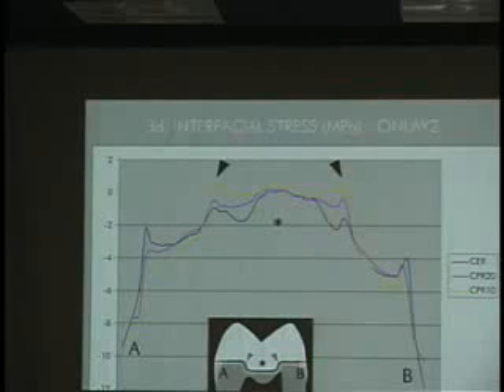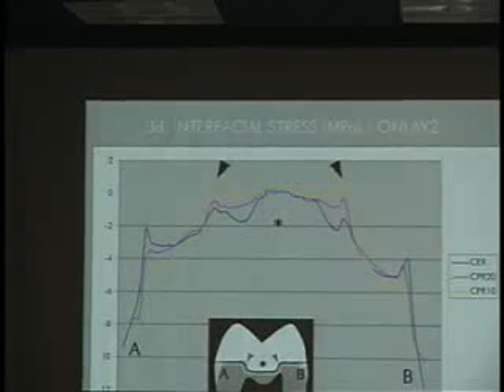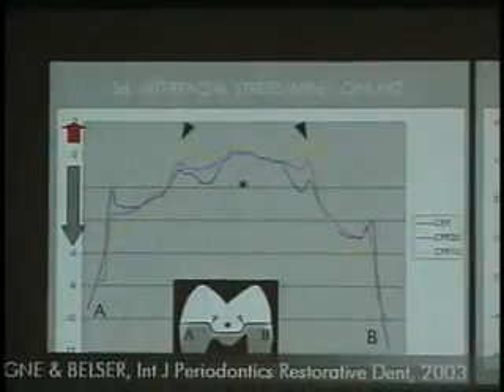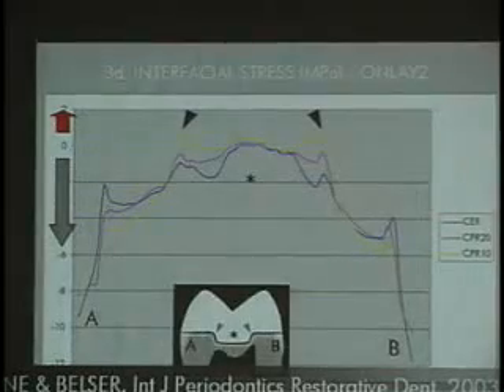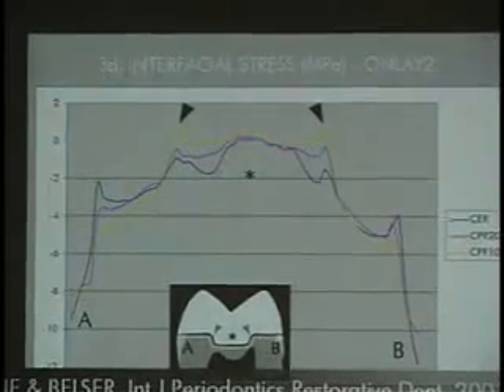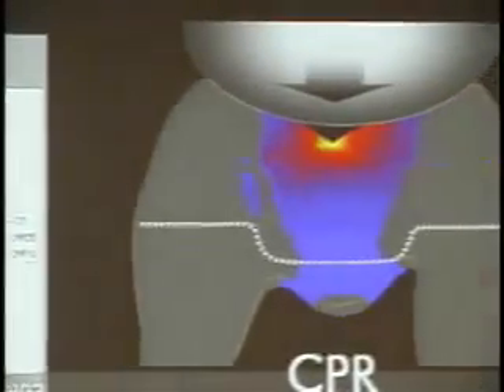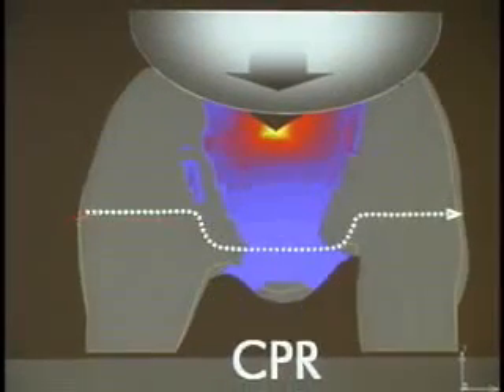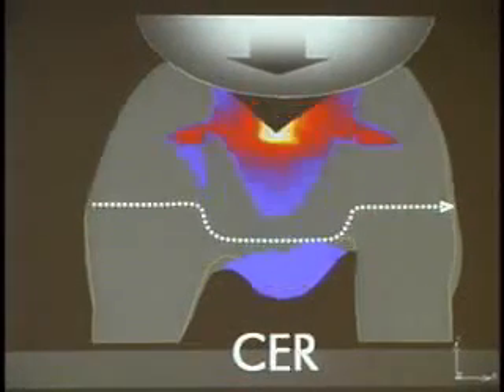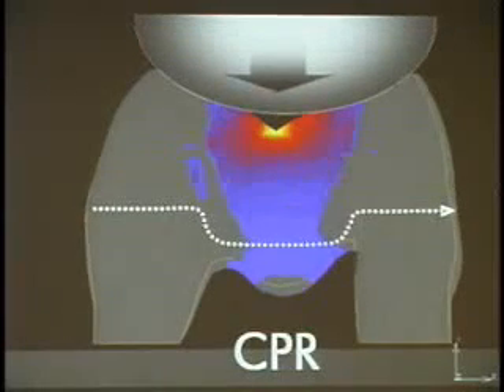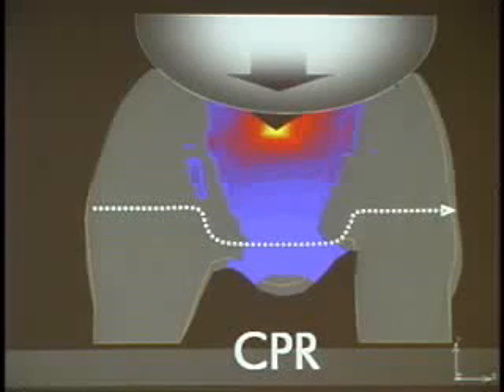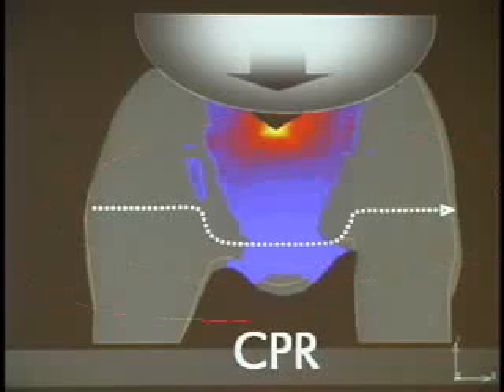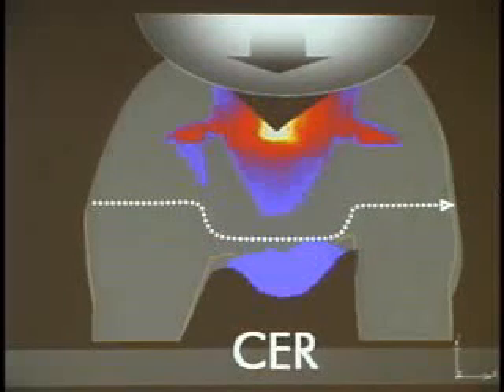While when you do an onlay restoration, most of the interface is under compressive stress. And that's why the onlay type restoration is a very strong concept. Maybe the bond strength in these cases is not so critical because most of the time the interface will function under compression, while the inlay is a more critical area because there are much more tensile stresses at this interface. When you look at the difference between composite and ceramic on the onlay type restoration, and this is really the beauty of finite element, to compare materials side by side, you can understand that there is more floppiness, more cuspal deformation with composite. However, on an onlay restoration, the bond is mainly subjected to compressive stress, the gray area, or very little tensile stress. On the porcelain, you see the interface is almost only compressive.